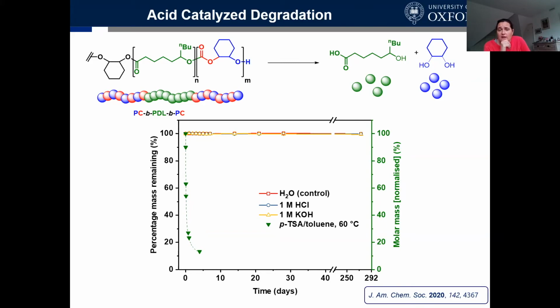That's not okay. But what we can do is when we've finished with using that plastic, we can control its degradation. In this case, we're using a little bit esoteric conditions in a lab, but we're using a pH 3 from this PTSA, toluene sulfonic acid, and we're doing the reaction in toluene with a bit of heating. But once we do that, then within a few days, 5 days, we've completely broken down the polymer. And of course, if we wanted that to happen within hours, we would simply conduct it hotter as a reaction, and that would be very feasible.